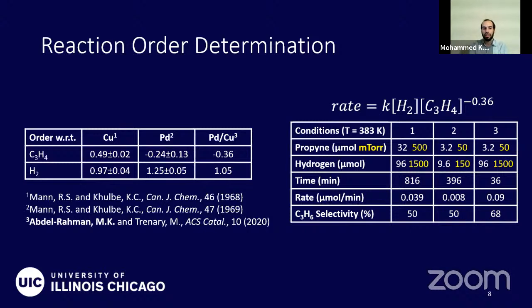Compared to literature values, we find that the value for the single atom alloy is most similar to that of pure palladium and not pure copper. And so we found that to be quite surprising, actually, given the fact that we have palladium as 2% over the whole catalyst surface.